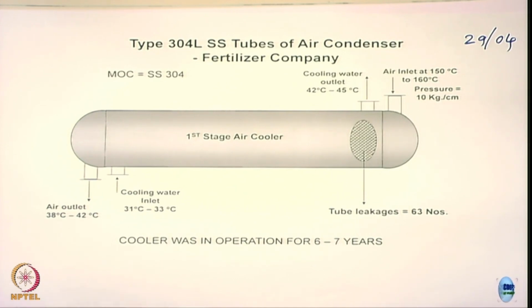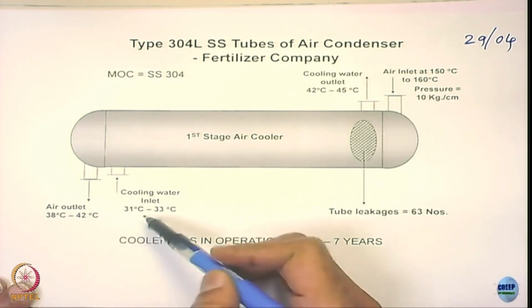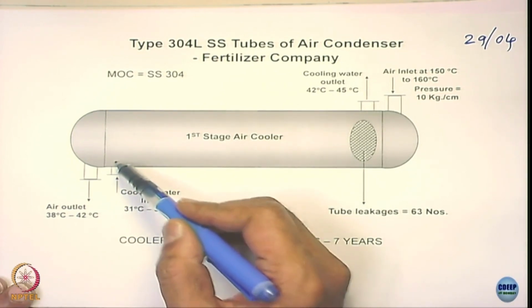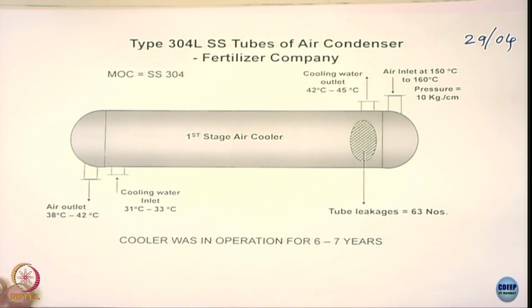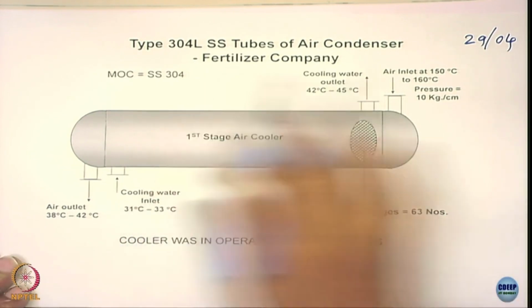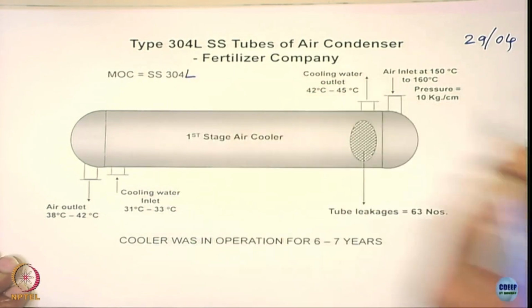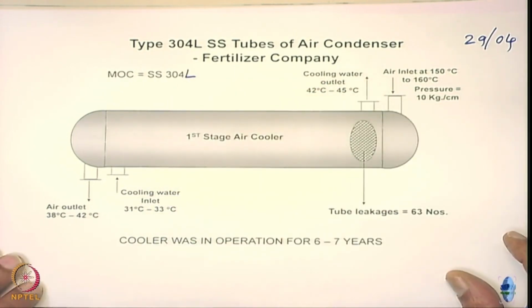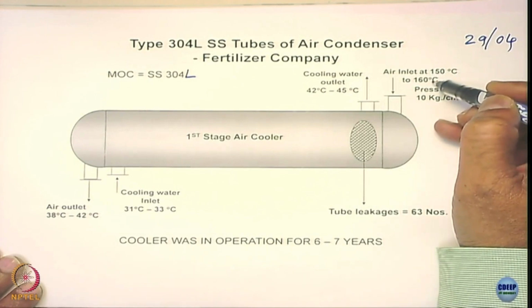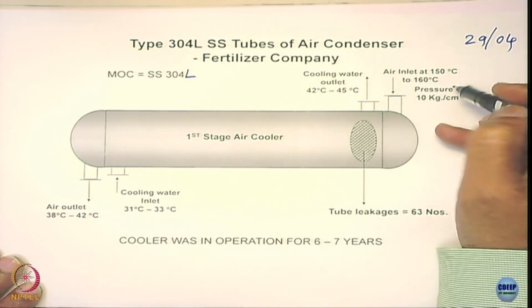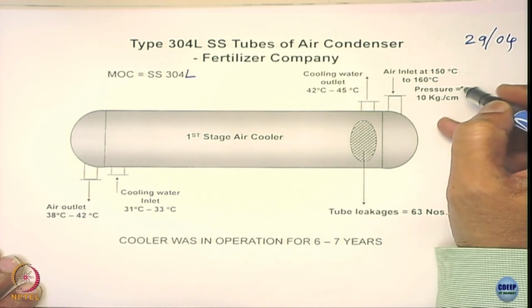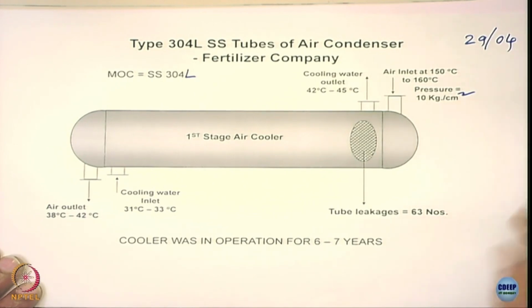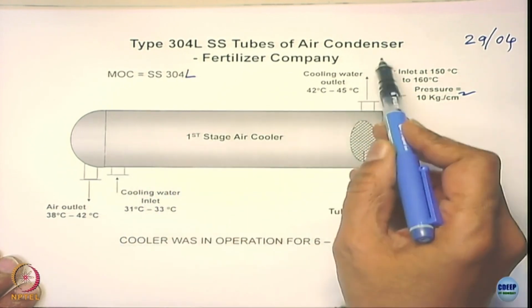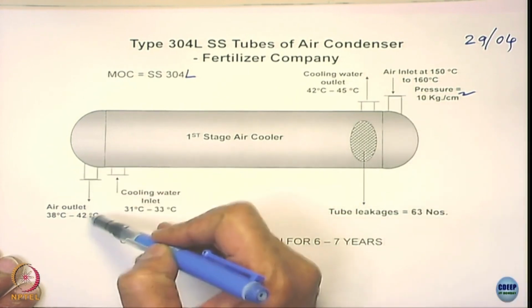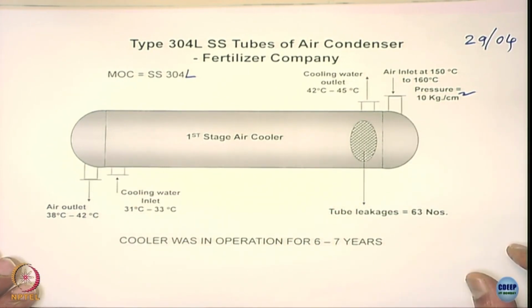cooling water system, okay. So what you do here is that you can see here that there is an inlet here, okay, it goes inside, this outlet here, and it is a horizontal heat exchanger, and it is made up of 304L stainless steel. The air inlet temperature is about 150 to 160 degrees Celsius at a pressure of 10 kg per centimeter square, and you have a cooling water, enters here and comes out, air enters here and then it comes out here, okay. It is a counter current process, right, it is what happens.